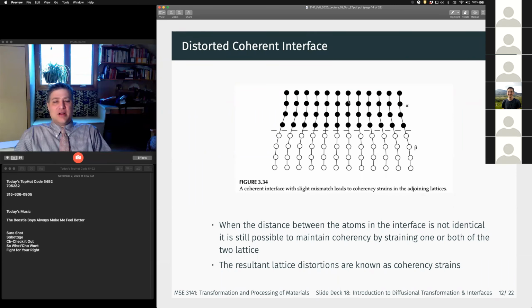I have a distortion. Near the interface, my A atoms are at a slightly different spacing than they would be in the bulk. And the same thing with my B atoms near the alpha beta interface, right? Here I have a tensile strain because these atoms are slightly farther apart than they would be back here. In B, I have a compressive strain because these atoms are slightly closer together than they would be back here, right? So I now have a distortion or deformation in my crystal, and this comes with an elastic energy cost, right? I have to stretch all these bonds from their equilibrium positions, and that means I have to pay energy to do this, right?